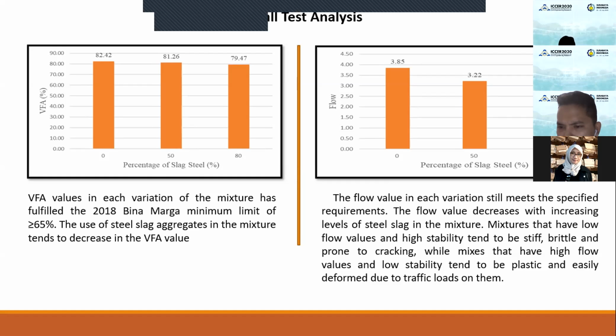Mixtures that have low flow values and high stability tend to be stiff, brittle, and prone to cracking, while mixes that have high flow values and low stability tend to be plastic and easily deformed due to traffic load on them.